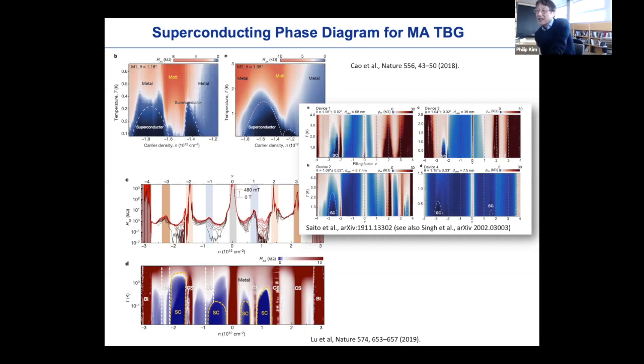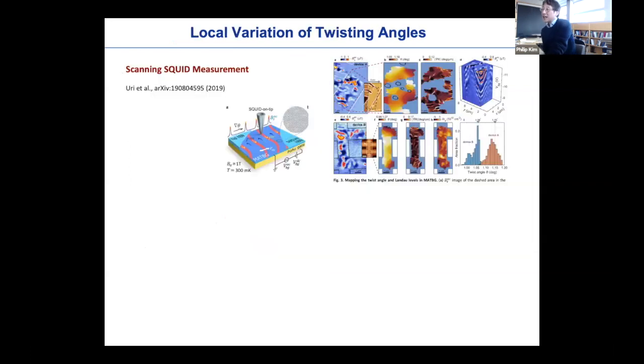So the issue here is how we can precisely control the sample we are studying. I think that could be one of the issues. It actually ties in with even one sample raising some issues: how well we can control the angle within the sample. Of course, if the physics is really sharply tuned by the twisting angle, in other words by the moire superlattice size, it must be quite important to have a uniform distribution of this angle, at least within the one sample that we study.